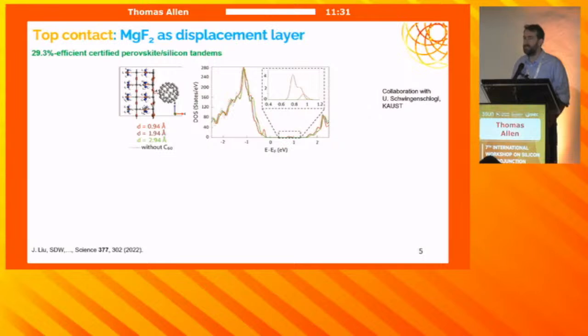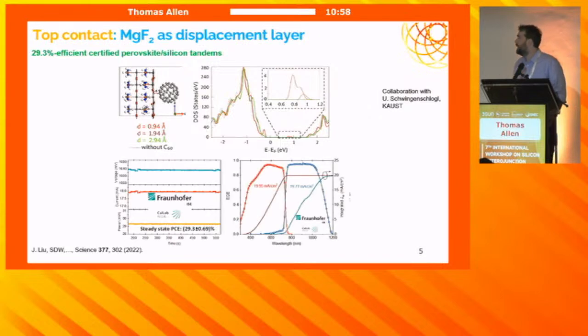And so the magnesium fluoride layer essentially is used to displace the C60 away from the perovskite interface. And for the silicon people, this is analogous to the defects that a metal will induce at the silicon interface, metal-induced gap states, let's say. Perovskites have a similar thing with C60. It's like a C60-induced gap state. So this is some DFT calculations showing the introduction of defect states within the band gap as the C60 is brought closer and closer to the perovskite surface. So with that, we were able to achieve a 29% cell, and obviously with some other optimizations.